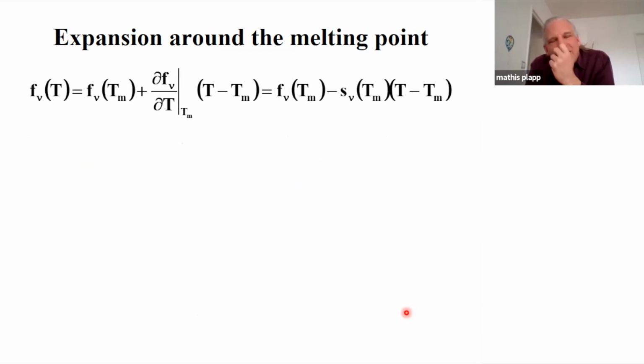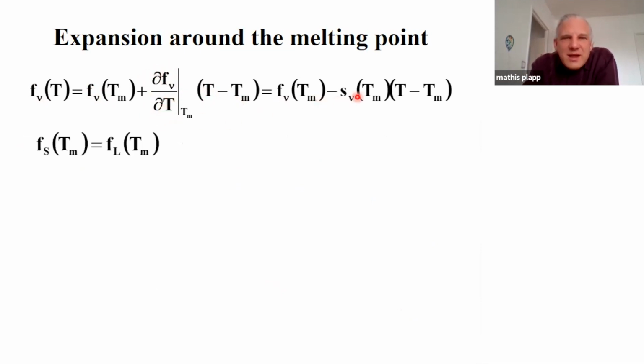Okay, and then if you say, okay, I'm interested in temperatures close to the melting point, then I can do a Taylor expansion of this free energy density around the melting point. So this is just a first order expansion in the temperature. And I can use that this coefficient is nothing but the entropy density. And then I can use, so here the index nu means solid or liquid. And I can use that actually for a pure substance, the free energies are the same at the melting point.